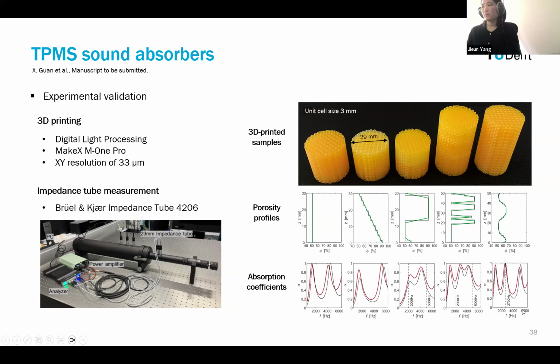And then the one at the bottom shows the absorption coefficient. These dotted lines are from our theoretical model, and these red lines are from the measurement. And you can see that the theoretical model and the measurement results match quite well, but there is also an increase of the sound absorption coefficient in the measurement ones, because when we actually print those samples, they cannot really replicate the size and the geometry very precisely, so they have a little bit of increase in the dissipation when we actually print those samples.